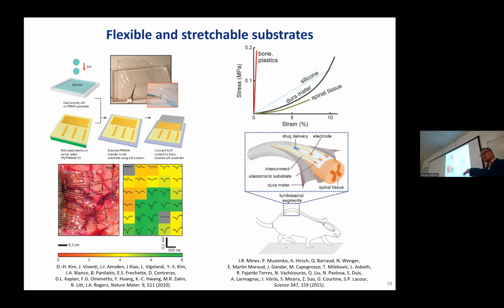So it's like tattoos for the brain, the surface of the brain, giving you excellent mechanical contact with zero mechanical loading. This is from Stephanie Lacour's group in Switzerland. She used elastomeric substrates that are stretchable. And then you can develop electrodes on them, and they follow the motion of the body. So if you put them on the spinal cord, as you go around your daily activity, the spinal cord will expand by up to 10, maybe more, 15%. And these arrays can follow that motion.